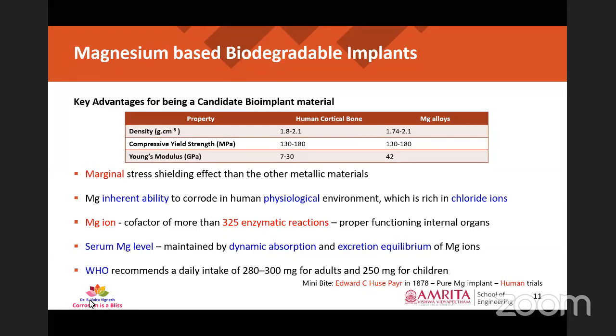Added to that, magnesium has inherent ability to corrode in the human physiological environment, which is rich in chloride ions. Even if this magnesium goes into the body, it will create magnesium ions, and these magnesium ions are cofactors of more than 325 enzymatic reactions within the human body. That will ensure proper functioning of internal organs too. Added to that, the serum magnesium levels will be maintained by dynamic absorption and equilibrium mechanism of magnesium ions by the normal human body functions itself. The World Health Organization also recommends a daily intake of 280 to 300 milligram of magnesium-based salts for adults and 250 milligram for children too. So these factors make magnesium alloy one of the candidate materials for bioimplant applications.